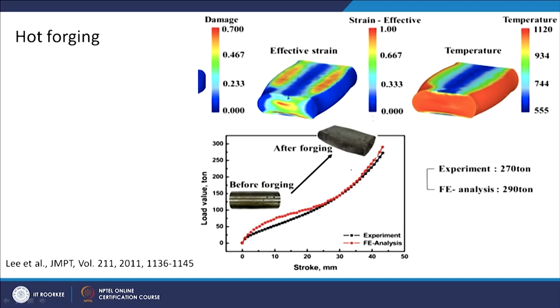As you can see, the effective strain is plotted here and the color coding is given here. Blue is very low strain, red is very high strain, and they are trying to show where the high strain is achieved. So basically the idea is that in the same deformation process, you achieve different levels of strain and strain rate in the material. So understanding of the thermomechanical process is very important to know whether you are reaching a deformation condition which can introduce a defect in the material. So we have to be very careful about that.